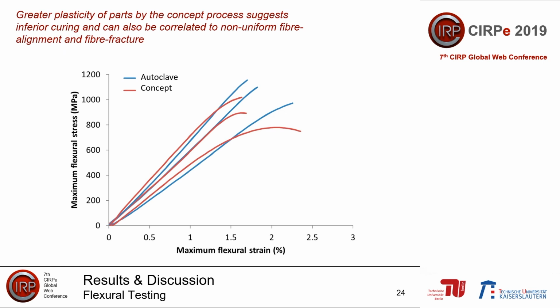If we look at the flexural properties, the flexural testing, so in red we have parts produced by our concept process, in blue we have benchmark parts produced in the autoclave process. In terms of the flexural stiffness, then the properties are quite similar between the two processes. Also, the flexural strain to failure is quite similar between the two processes. However, where there is a difference is that in our concept process we have greater plasticity to the parts. Now this would suggest inferior curing behavior during our concept process. Also, we can see that parts produced in our concept process have around 80% of the flexural strength of the parts produced in the autoclave. Now this could be related to the non-uniform fibre alignment and the fibre fracture, as we saw on the previous slides.